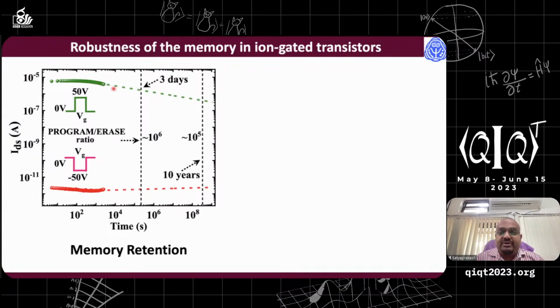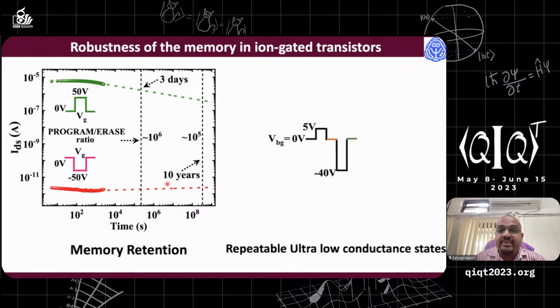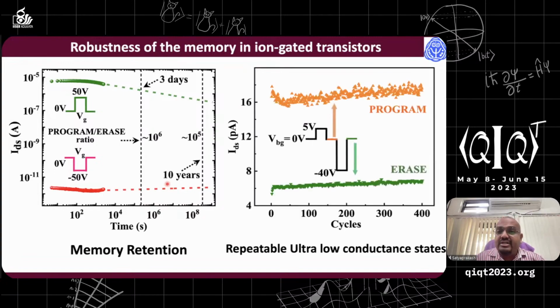And if you extrapolate it, and this is the way people are reporting, if you extrapolate this result, you can see these devices, once they go to a conductance state, can stay even for 10 years. Because we cannot test it for 10 years for the devices, but this is how people are doing. And this shows this device is quite robust. Once a memory state is achieved, it can stay for a long period of time, and they are promising for memory application.